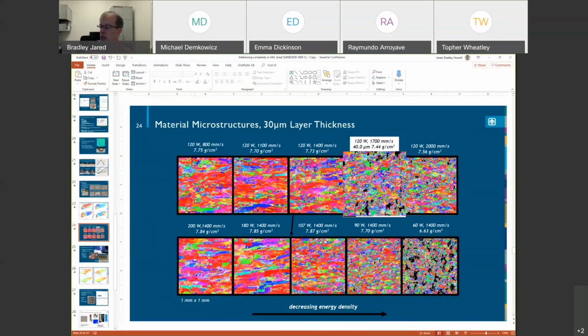So that's going to be a distribution that's going to look very similar in both in terms of size and shape. When we start looking at the far right side of these, where we're seeing these porosity defects, you're absolutely right. That's going to be an area where we are going to see larger variation because we have these porosity and void defects. And so, yeah, you want to make sure you're not on the right side of this plot, and you want to make sure you're on the left side. If you're on the left side of this, again, you're going to get fully dense. But this is why I said density is not necessarily the best indicator of goodness of the process. It may be good enough, but it may not really be where you want it to be necessarily.